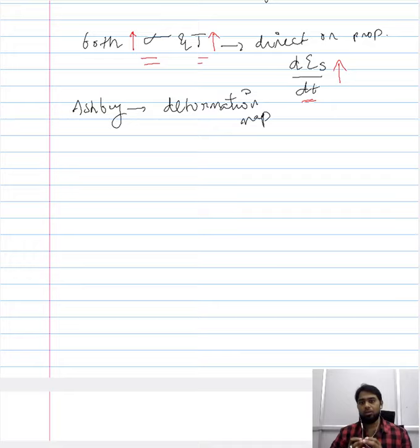So when someone wants to see at what rate his material would deform for a given combination of stress and temperature, instead of calculating the creep rate, one can decide which mechanism is operational, and based on that mechanism he can use the characteristic relation for that mechanism and calculate the creep rate that he can expect for that combination of stress and temperature.